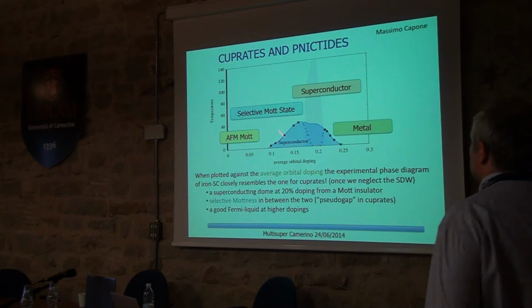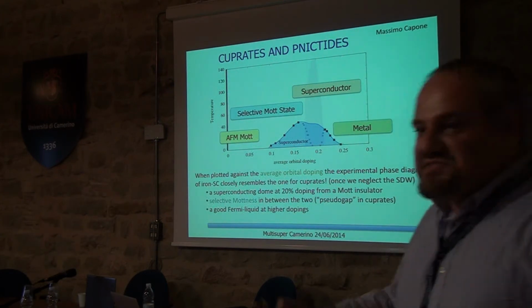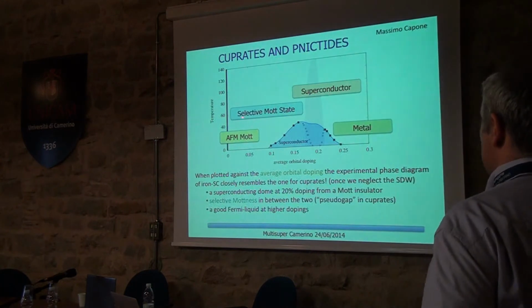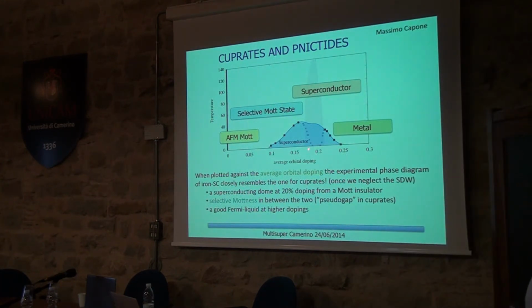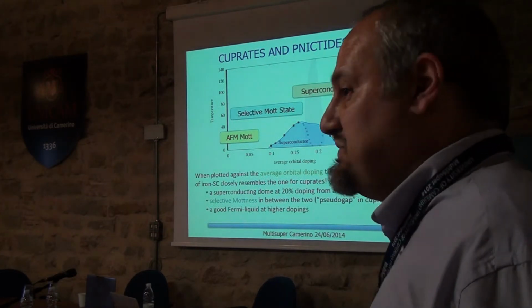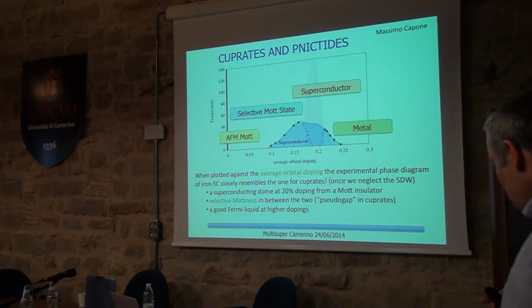So now I can come to a final thing, where this is the twist, where I try to unify the phase diagram of cuprates and pnictides. This is the experimental phase diagram for the 122 as a function of what? Average orbital doping. In my picture before, it's essentially here, this would be 0 because we have 5. So this would be 6, which means 0.2. So it's 6 over 5 minus 1. And you see that if I play the simple game of joining together the two superconducting domes, I have one single superconducting dome right where the high-Tc superconducting dome is centered. What do I mean here?